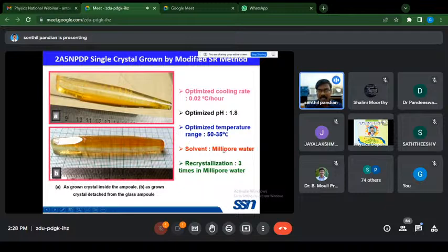Normally in the SR method, we evaporate the solvent and grow the crystal, and this is a different kind of crystal growth we have made, and we have successfully grown the crystal. We made a slow cooling run, and we prepared the solution at 50 degrees Celsius. From 50 to 35 degrees Celsius, we reduced the temperature, and we successfully grew the crystal with a cooling rate of 0.02 degrees Celsius per hour.